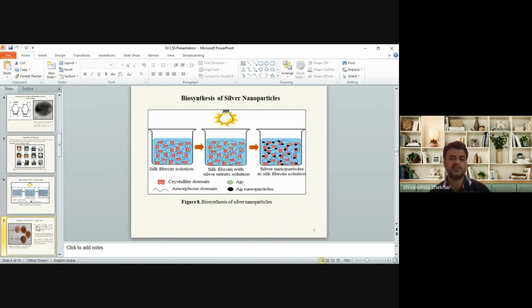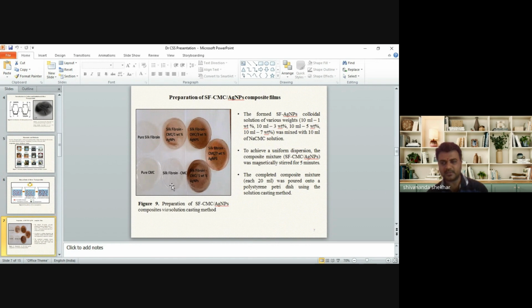Later, in the next step, we took the silk fibroin and silver colloidal solution and mixed it with 10 ml of carboxymethylcellulose solution. So we made composite films, that is the pure silk fibroin film and pure carboxymethylcellulose film, with different concentrations of silver nanoparticles embedded in the silk fibroin as well as the CMC composites. This is the schematic representation for preparation of the SF CMC AgNP composite solution via the solution casting method. This is the obtained composite films. We have gone for different characterization techniques in order to study the properties of these composite films.